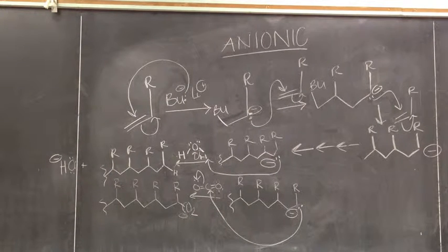Anionic polymerization is initiated in the presence of a highly reactive anion, such as butyllithium. The anion functions as a nucleophile and attacks the pi bond of a monomer, thereby generating a new carbanion. The carbanion generated during the initiation stage then functions as a nucleophile and attacks another monomer. For monomers that undergo anionic polymerization, the process continues until all of the monomers have been consumed.